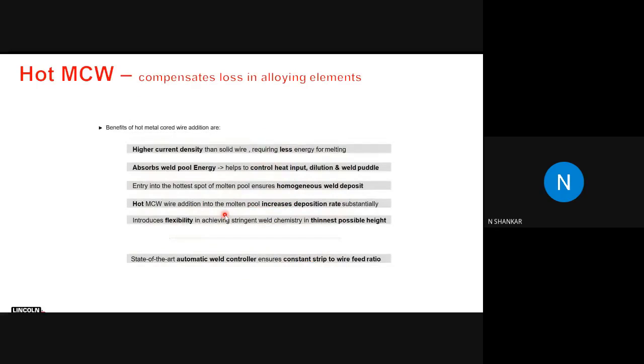Now, when we come to the hot metal core part of it, what are the advantages by adding it? It can compensate loss in alloying elements by adding alloy elements to the metal core wires. So this will take care of the chemistry of your end weld, and will give you a higher current. We have chosen metal core because metal core gives you a higher current density than solid wire, meaning it requires less energy to melt, and we are not preheating it. We are picking up the heat from the strip clad itself to deposit. It absorbs weld pool energy, helps to control the heat input, dilution, and weld puddle.